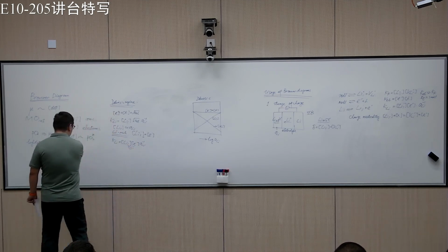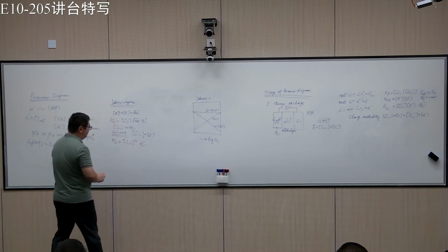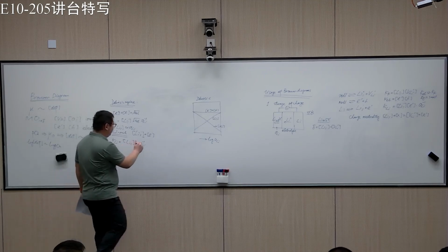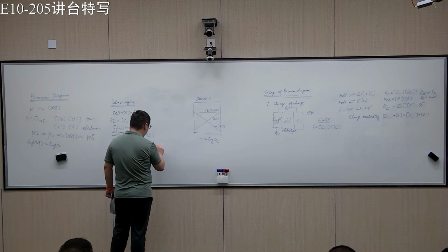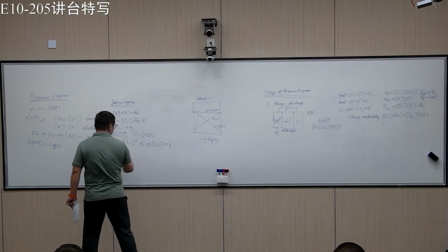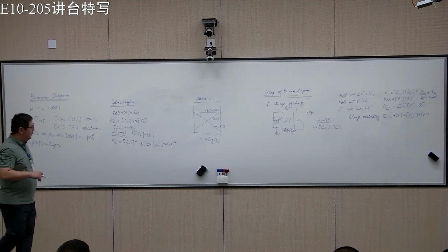We know these two are the same, right? So I can write it as the amount of this squared. All we need to know is the power law n here. So we can already see that in this case, it's proportional to the activity of lithium to the 1/2.